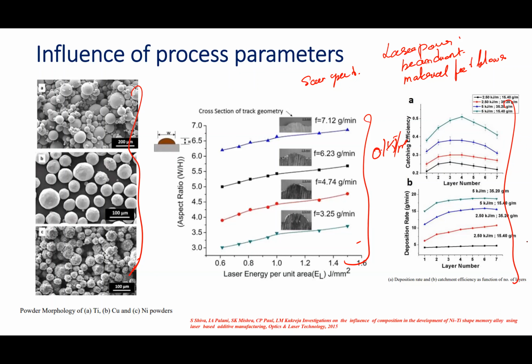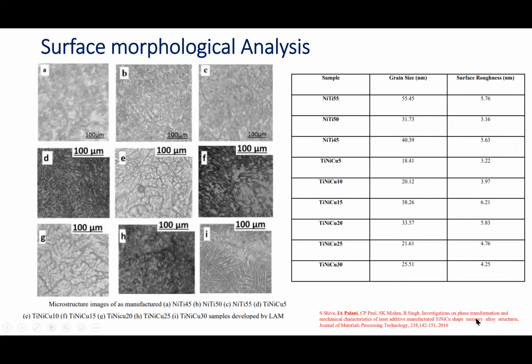It was also observed from this graph that an aspect ratio of above 5 was capable of depositing a defect-free track, as it avoided the inter-run porosities generated at the base of the track due to the lack of fusion zone. Hence the process parameters yielding an aspect ratio of more than 5 were chosen for the experiments. Okay, now these are some of the surface morphological analyses which we have performed with respect to these structures.